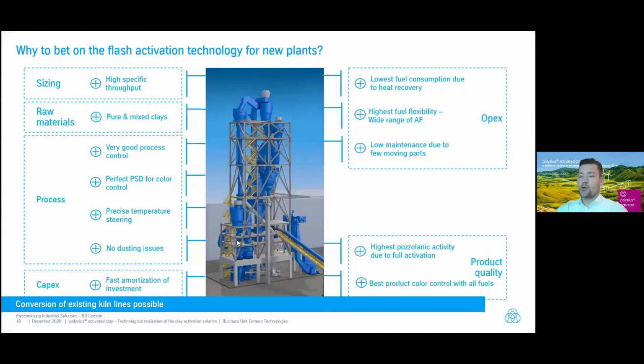For sure, we have to prepare our clay here for our process to make the clay flyable. So for this, we are using a hammer de-agglomerator. But this is nevertheless needed. If you talk about color control, you cannot control the color of a clay which is quite coarse. So in any case, you have to bring the clay to a quite fine particle size to do color control. If you go for a flash or if you go for the rotary kiln, that doesn't matter. So also this cannot be seen as a disadvantage in our system.